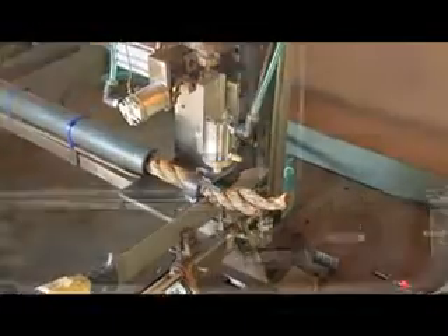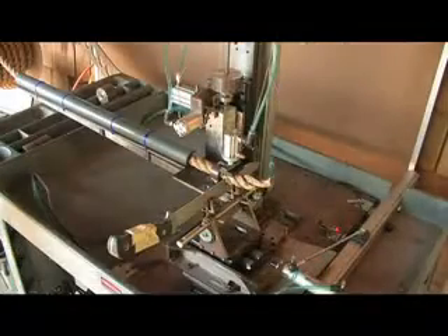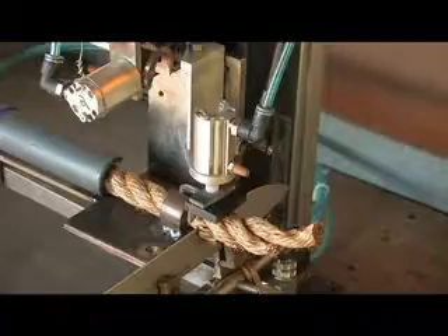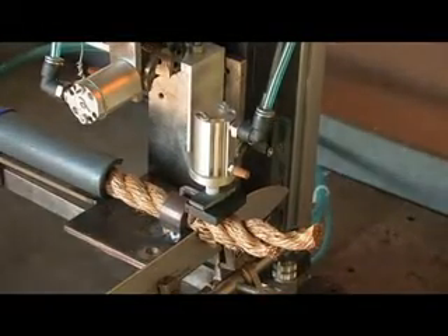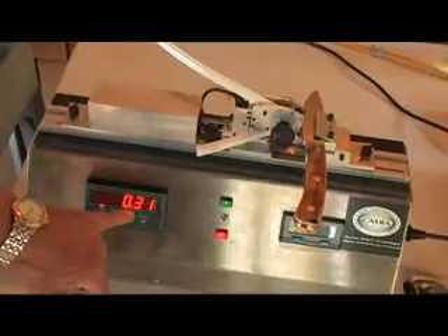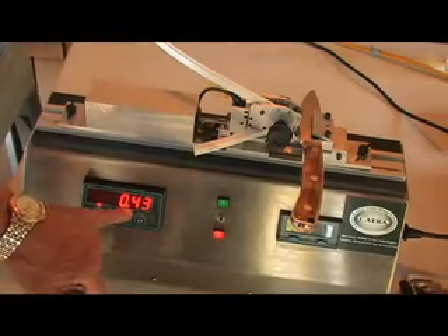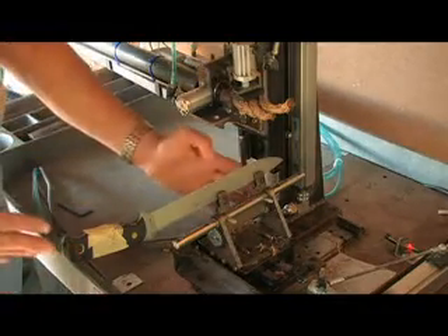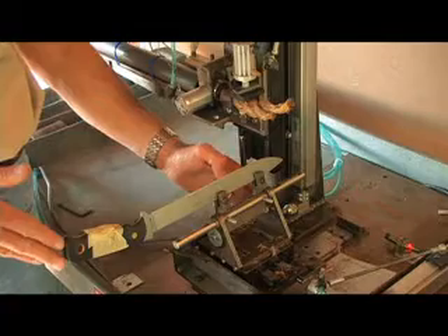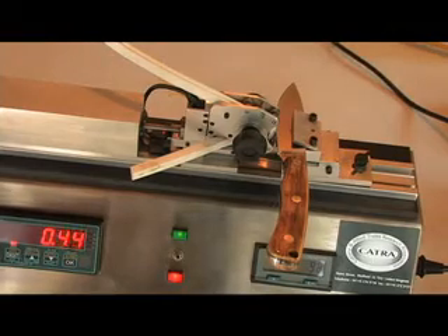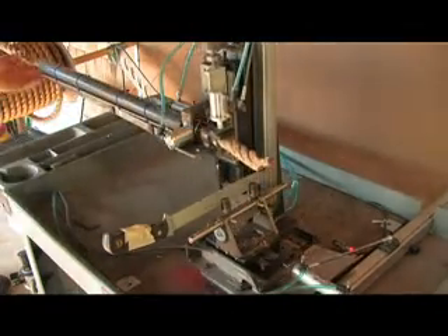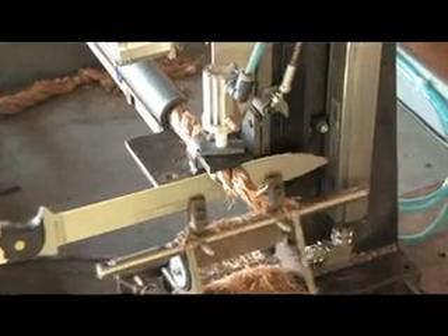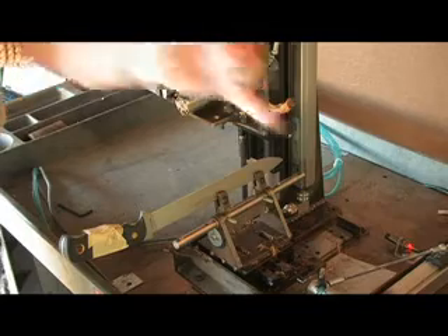We continue to use this as a means of wearing the blade, so we don't have to wear it by hand with a chop. That's our old chop tester. So we actually modified this, got rid of the silicone paper, and went to rope. We say when it's 3.0 or greater, it's no longer a usable blade. What we would find with materials other than friction forged materials is that with these cuts on the rope, a 3/4 inch standard manila rope, it would dull, as those graphs indicated, much quicker than the friction forged. So with the friction forged, we'd run the test, put it on the REST, conduct the test back and forth, and we'd find that we were up in the hundreds and hundreds and hundreds of slices before we get to 3.0.